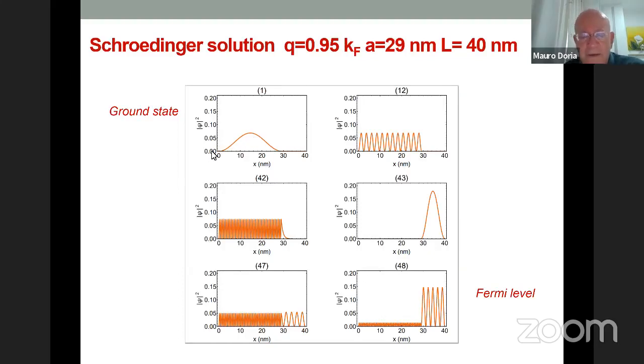Since the Anderson approximation tells me to first solve the Schrödinger equation, you see that there are 48 levels. The more fundamental levels are localized inside the nickel bismuth 3. But when they get near the barrier, states begin to percolate to the bismuth side, such that for 42 to 43 you finally have a state that's totally localized in bismuth. Then at 47, they begin to coexist on two sides, and you have things even concentrated on bismuth.